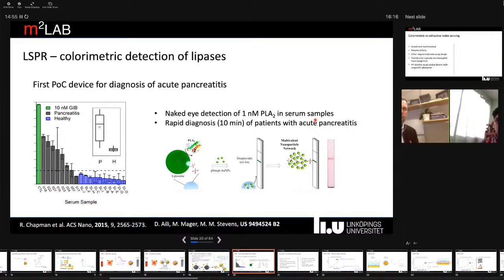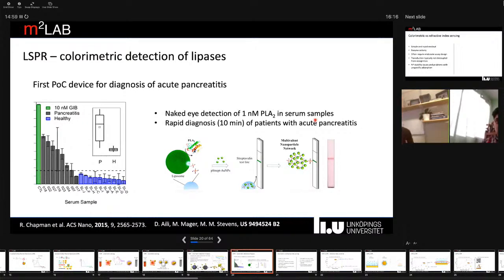This was then later developed further together with collaborators into a device for diagnostics of pancreatitis, where you have quite a large overexpression of lipases. This is an acute pathological condition which requires immediate attention by a physician, or you need care within hours, essentially. So a rapid diagnostic here is key for the correct treatment. And with this lateral flow device based on this concept, it was possible to diagnose pancreatitis in patients in serum samples within 10 minutes.